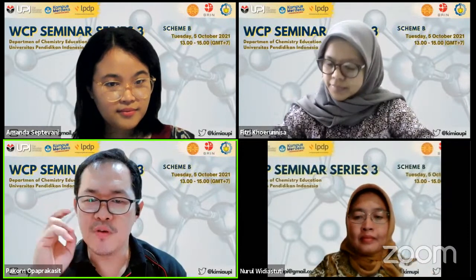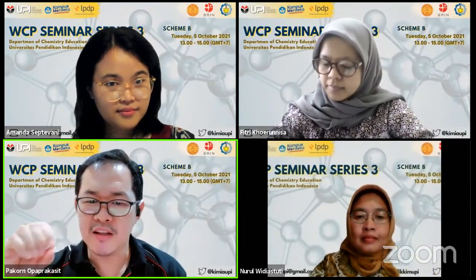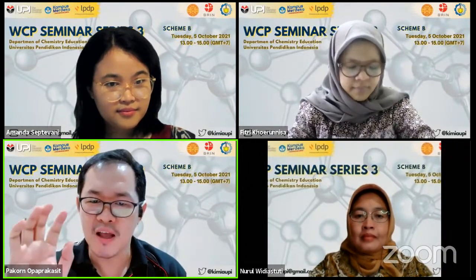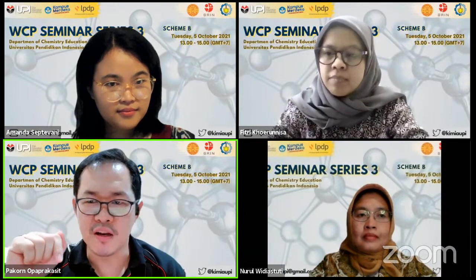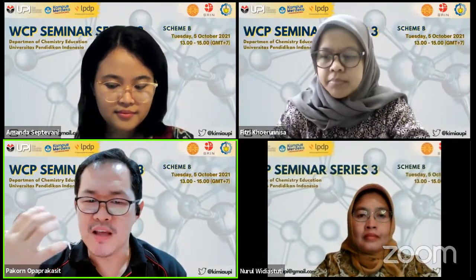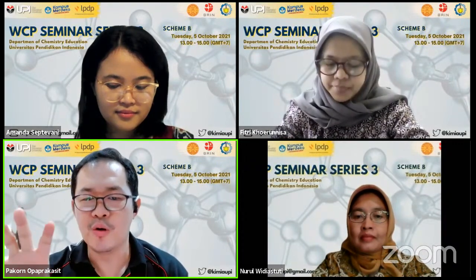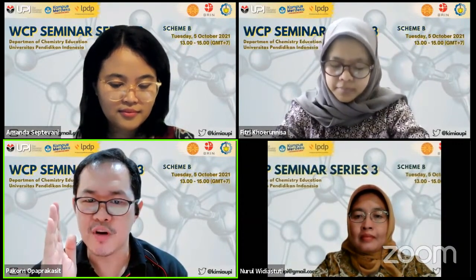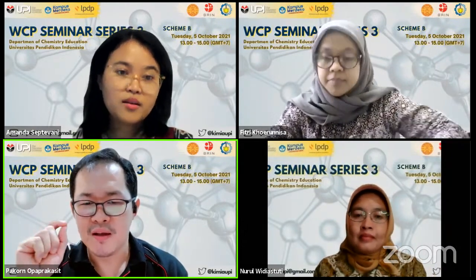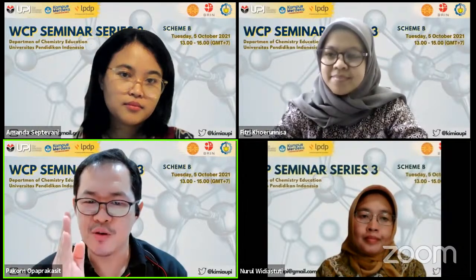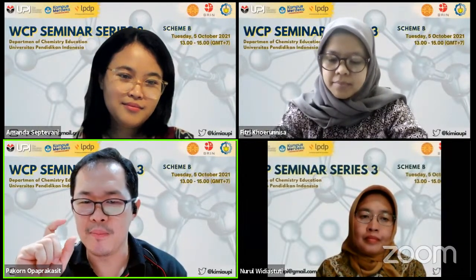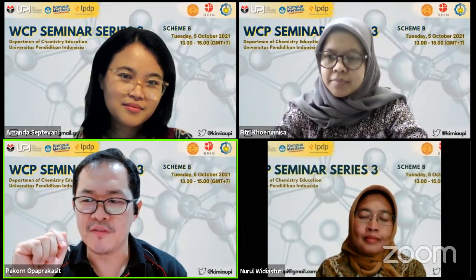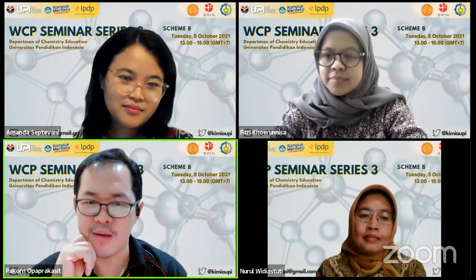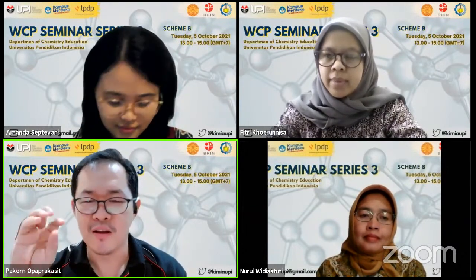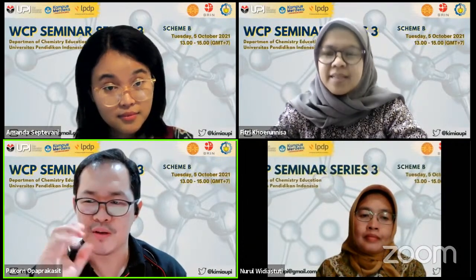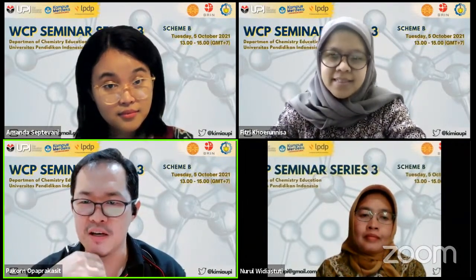for us, right? So if we measure at the same spot, at 0 and 90 degree, if the spectra have no difference between these two directions, it may mean that our sample is isotropic, right? So no orientation of the structure. But if we see a difference in the spectra at 0 and 90 degree, now we know that there is some specific orientation of the crystal structure or certain functional group in the sample, right? So if we know this, we can then go further into the detail. So that is the importance of using a polarizer in the measurements.